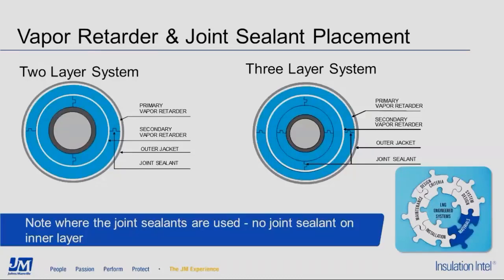Thanks, Jim. So jacketing. The primary purpose of the jacketing systems for all installations, but particularly the low temperatures we see in LNG, is that it protects the system, and especially the vapor retarder, from damage from physical abuse, punctures, and even the UV rays from sunlight. The jacketing most often used is aluminum and stainless steel, and in many applications there's more stainless steel jacketing than aluminum, because in a lot of the areas where you see the LNG installations, they're in very corrosive environments, and there are also areas with high flammability concern.